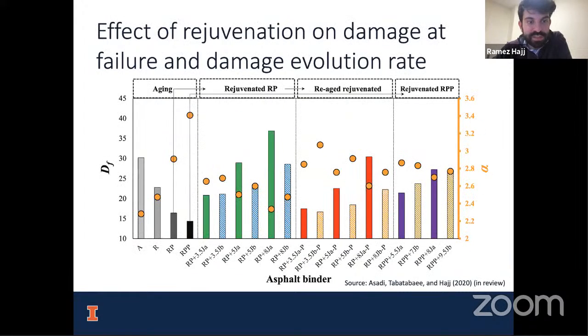The first thing we looked at is the damage evolution. You can see here that the damage at failure of these binders is about 30% for an unaged asphalt. A represents unaged, R is short-term aged, RP is long-term aged, and RPP is doubly long-term aged. So this is increasing levels of aging. You will see that it takes less and less damage to fail the material. But then you can see as we rejuvenate it, it starts to go back up, right?